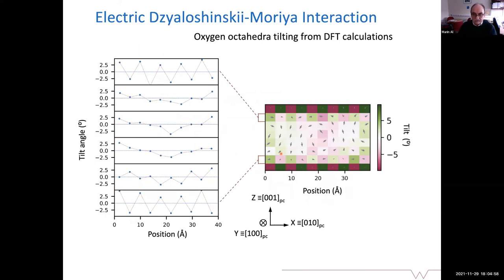So where is this coming from? We analyzed our DFT results in terms of the oxygen octahedra cage tilting. We know that strontium ruthenate has an opposite tilting in every unit cell. It's like a checkerboard structure, and it's quite strong. Each unit cell has about 2.5 degrees tilting of oxygen octahedra. Looking at the oxygen octahedra tilting within the polarization layer, we see that we have quite an important tilting at the interface.